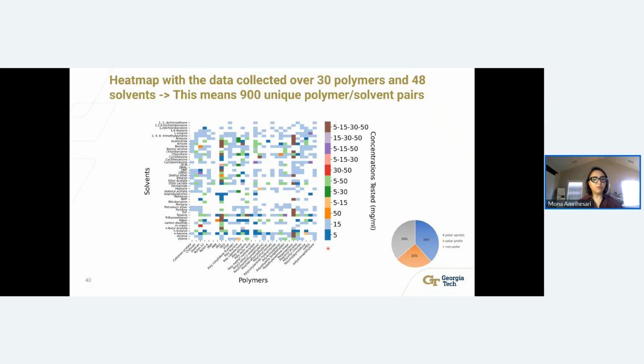For most part, for faster data collection, we selected 15 milligram per milliliter. The reason for that is that this is not very dilute system, and more industrial processes are more interested in a little bit higher concentration, but not too high, because in the polymer solutions, the too high will come with some kinetic complication as well.